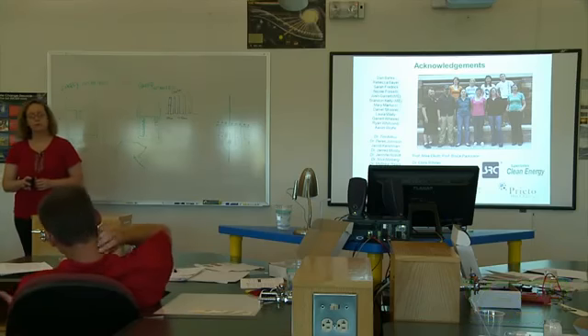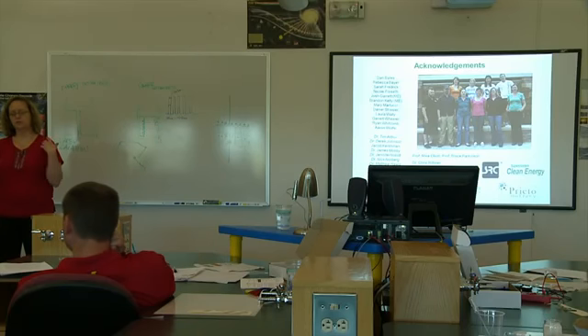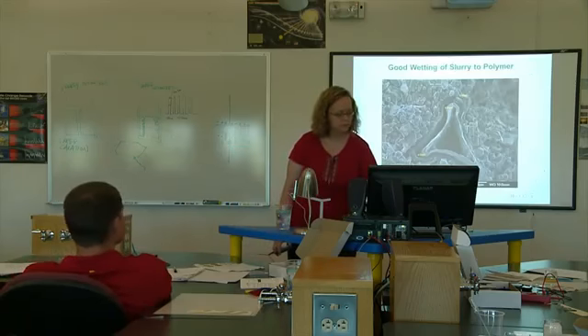How is the foam formed, harvested, collected? So we buy it from a company. Originally, we were buying it from a company from the Netherlands. Now we're actually buying it from a company in China. And the way they make it is first they pressure extrude a molten polymer that when it cools, it gets all these air pockets in it. Then they use a chemical process to coat that with copper. And then they burn off all the polymer and you're left with the foam. That's why if you look at this picture, the foam is hollow.